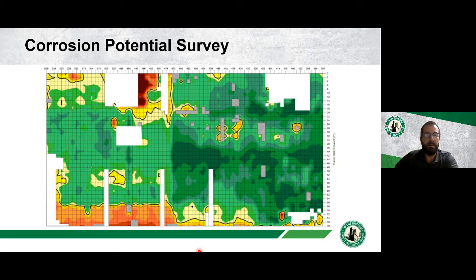Just so you're aware, this area is actually the entrance of the garage. This is the top level, level A. The levels are lettered, so A, B, C, D, E, and F. This is where the cars enter and exit the garage. And right here is the grade level where the roadway is. So obviously moisture and salts are coming in on tires from the vehicles into these areas, and that's causing a higher risk for corrosion activity. This area over here in the top of the image is near the elevator bank. In the winter months, they're putting ice melt down due to water and people's traffic here. So this is where you're getting more active corrosion as well. With these areas, we can identify where there is active corrosion and where there is current delamination with the hammer sounding.